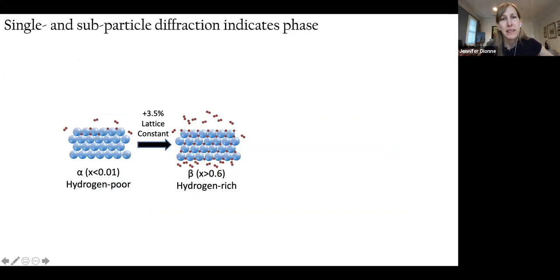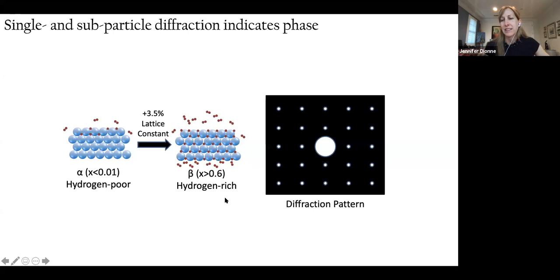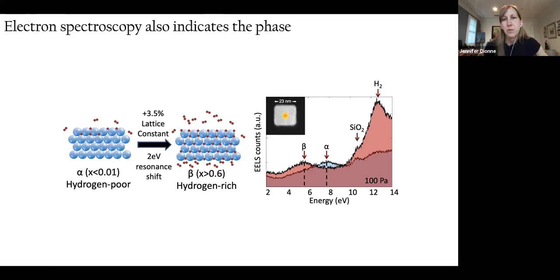So how is it that we're probing hydride formation? I mentioned that there's a change in lattice constant. So as we go from the hydrogen poor to the hydrogen rich phase, there's a 3.5% change in lattice constant. So that's obviously something that we can follow using conventional diffraction. And then similarly with electron energy loss spectroscopy, that's probing the band structure or the material's electronic properties.